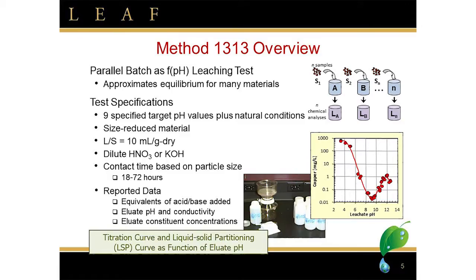The first is Method 1313. This was designed as a parallel batch leaching test to look at liquid-solid partitioning initially as a function of pH between the materials. In many environmental materials and waste forms, this approximates equilibrium conditions. However, for a glass material, we recognize fully that given the rates of the reactions that are occurring, we're looking at a partitioning at a point in time. We're not actually looking at an equilibrium case that's being achieved.